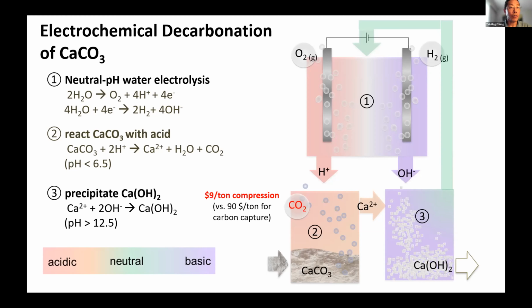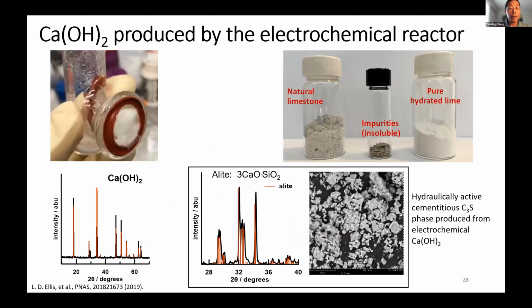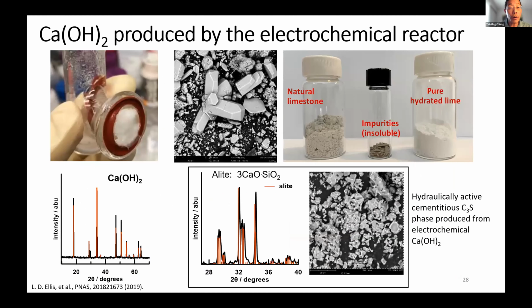So in this scenario, what we do is that we dissolve the limestone in an acid. Right? And we first did it with nitric acid, but HCl works just as well. And the dissolved calcium can then be precipitated to calcium hydroxide using the base side of the electrolyzer. Okay, so how does this all end up?